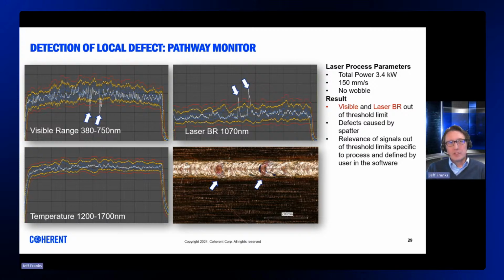Here, we can look at the same process results with zero gap condition, showing some localized defects. SmartSense Plus has detected some spike conditions out of range caused by the creation of some small spatter defects in the weld. This could indicate porosity generation inside the weld bead and should require further inspection by the end user.